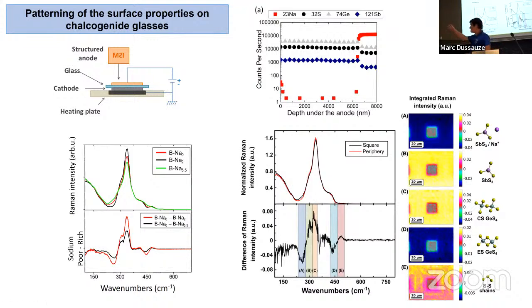So that proves, this similarity proves that this glass is very flexible. You can change the structure, move the sodium, insert it or not, and the glass structure will rearrange very easily. And the very nice thing is that you can do it at micrometer scale, which means that the changes of structure that we can map in Raman are very well controlled at the micrometer scale thanks to this imprinting method. So that's, for me, the most important thing that you need to remember: you need a glass that is flexible and where the poling can really arrange the structure without destroying everything.